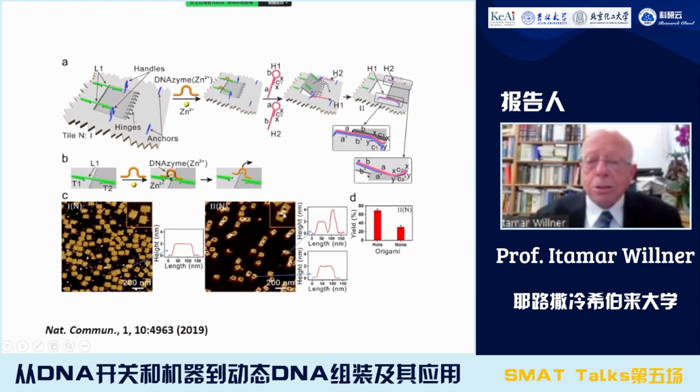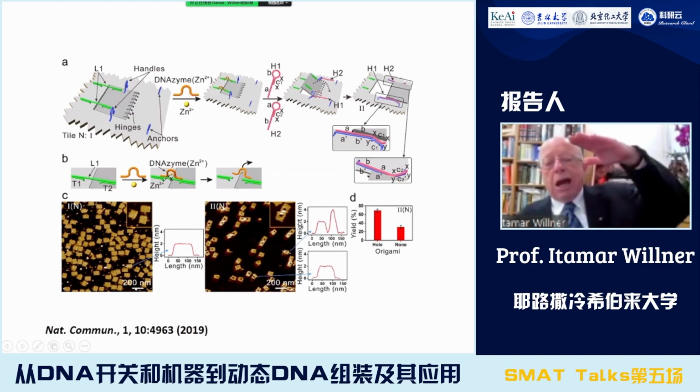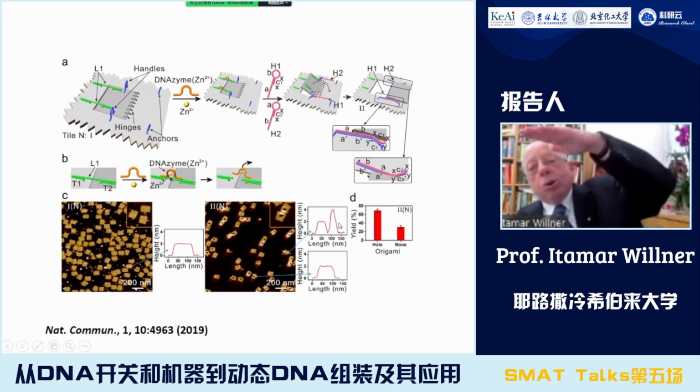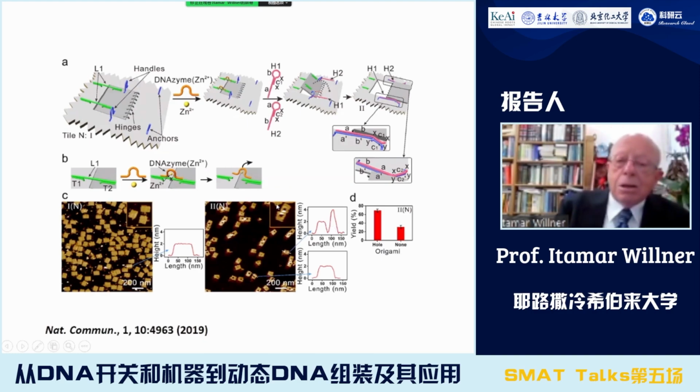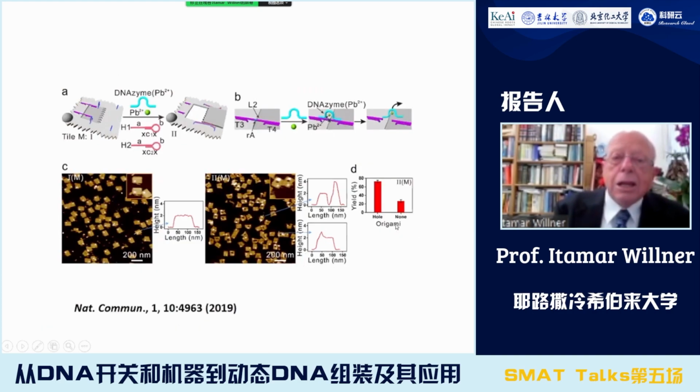When you open it, you can see here the hole, and you see here a bright spot. The bright spot is a higher origami, a double origami thickness region that can be seen by the cross-section analysis, where the window lies on the origami tile. So we have a mechanism to open the tile.